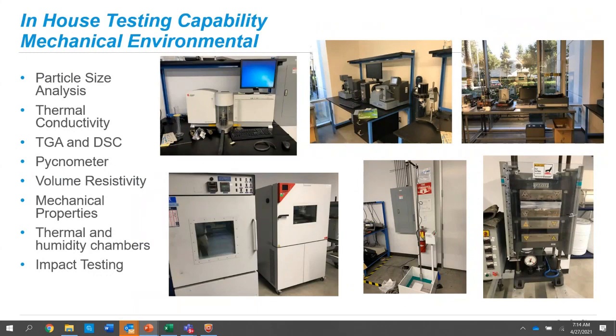The middle picture there on the top is thermogravimetric analysis and differential scanning calorimetry. That is a good test to look at these materials and how they do, it's kind of weight loss versus heating. And so you can kind of see how these things do at elevated temperatures. And what we found, when we're looking at higher temperatures and trying to come up with 600-degree Fahrenheit solutions for people, is that this long-term weight loss that the TGA can give us is a very good way to look at different materials and compare their performance.